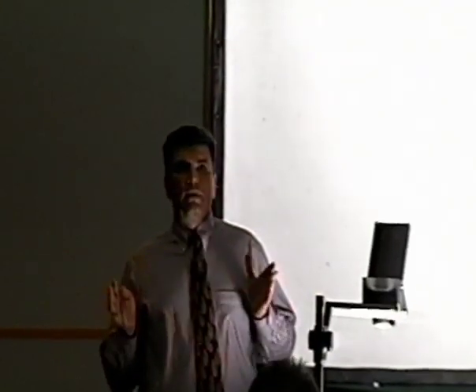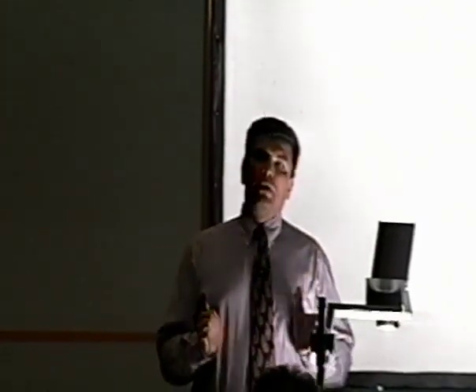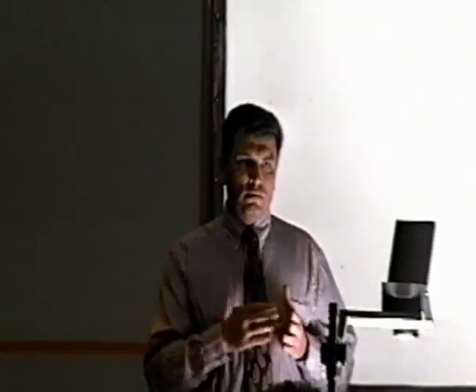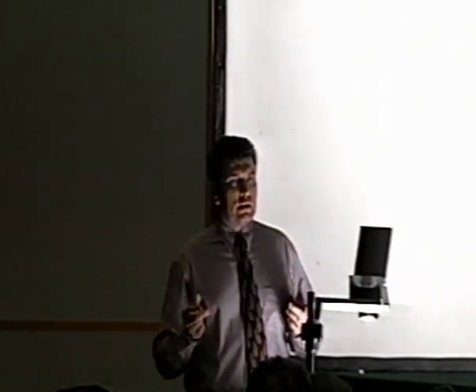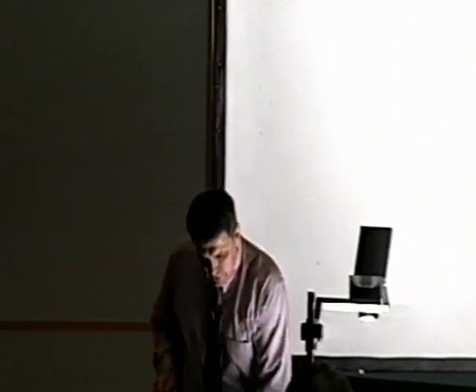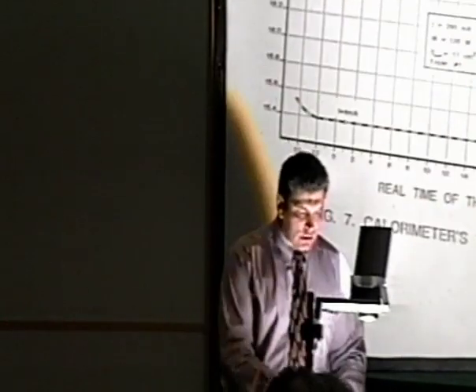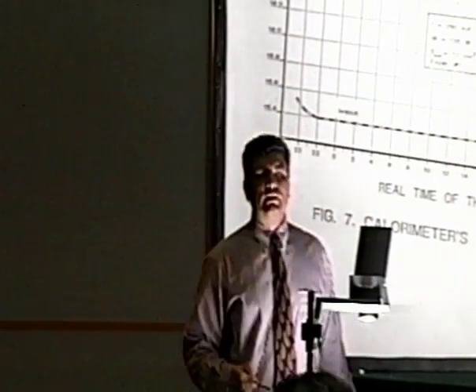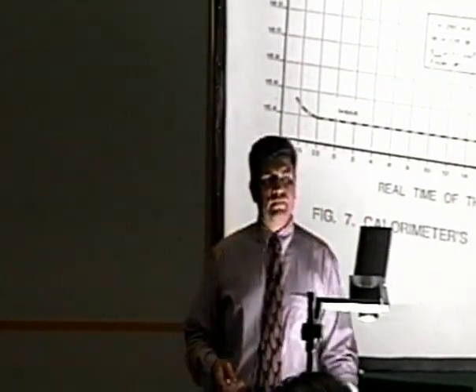And for how long? Each experiment was running about 3 days constantly. About 1.5 days we considered the loading period, and when we accomplished it, we started current cycling. The effect lasted about half an hour, and then decreased. This is exactly like in our plot, this is minutes, 10 minutes, and then it's done.